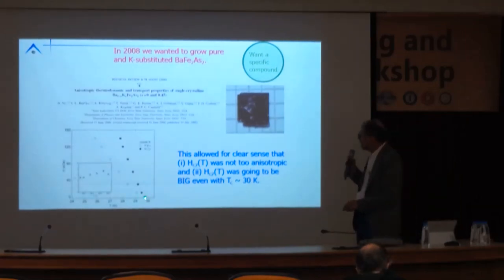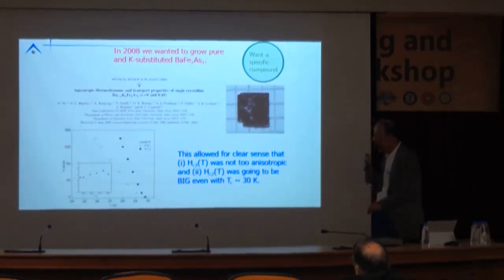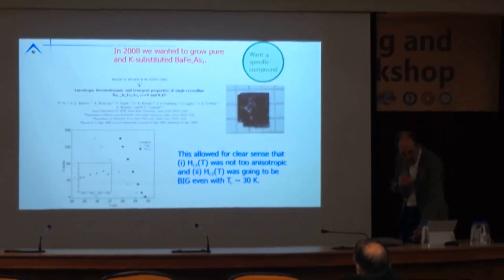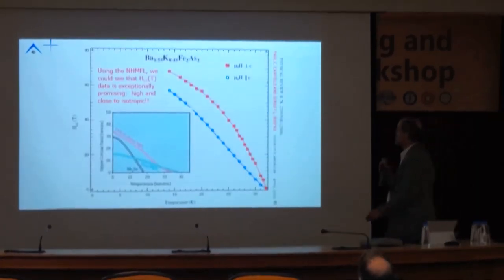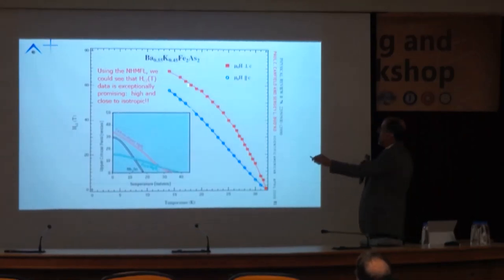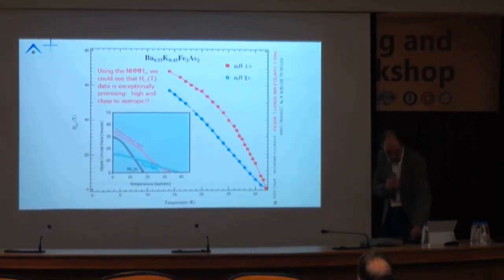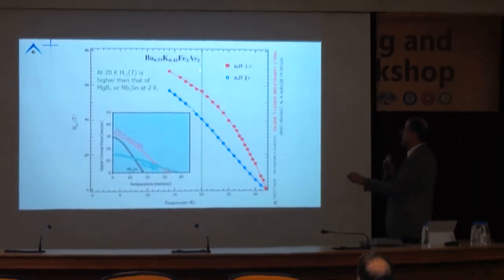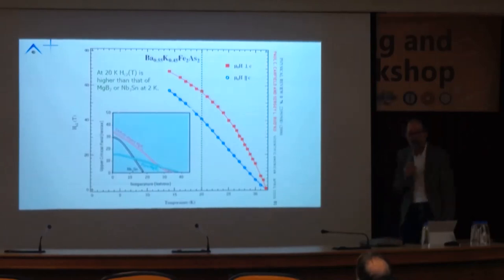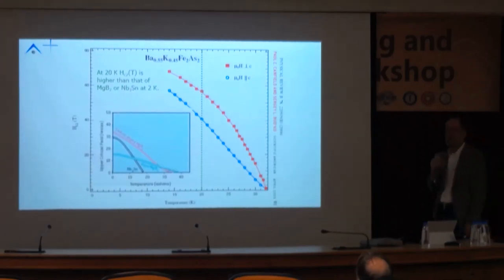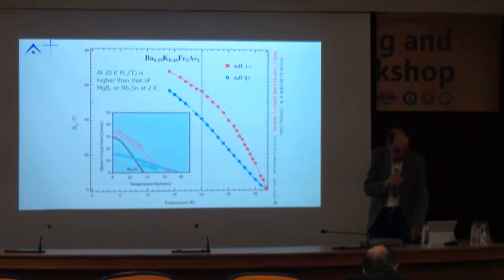What we can see is with a Tc slightly less than 30, even 14 Tesla only suppresses it to about 26 Kelvin. So Hc2 is going to be huge. In addition, this looks like a relatively small anisotropy, but we need higher fields. So we went to the National High Magnetic Field Laboratory, and we can see that indeed the anisotropy is coming out relatively small, but perhaps more importantly, we can see that at 20 Kelvin, which remember for MgB2 was nice because we could reach that easily, the lower Hc2 is in excess of 40 Tesla, in excess of anything MgB2 or niobium-titanium has to offer. Within a few months of discovery of these materials, it was clear they had potential as applied superconductors, in addition to being very interesting basic physics materials.